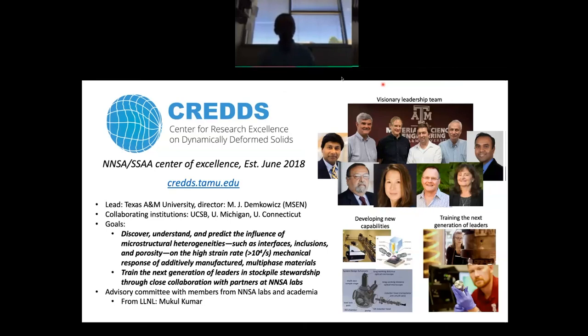And as a rule, I would say if you were to take any material off the shelf, think of any favorite material that you have. Maybe it's a high entropy alloy, maybe it's a perovskite, maybe it's, I don't know, a polymer or something. Almost any material that you're going to take off the shelf, we have no good potentials for. However, we have some materials for which we have very good potentials, okay? And the molecular dynamics simulations that I showed you today were done entirely on those materials for which we know we have very good potentials. And by very good, I mean not just good in the solid phase, but also good in the liquid phase.